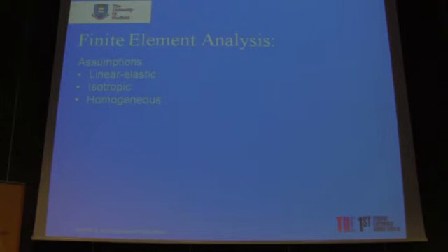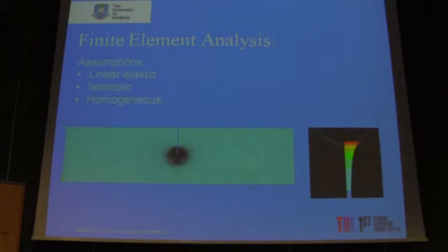TCD requires two components to be used: it needs the two material parameters and it needs an accurate stress field. So I've performed finite element analysis on the different models using the above assumptions. This is a typical example of a model that I've produced, and as you can see around the notch apex, the mesh density is refined. It's refined to a point where the stress, in this case the maximum principal stress, is converged at the critical distance.